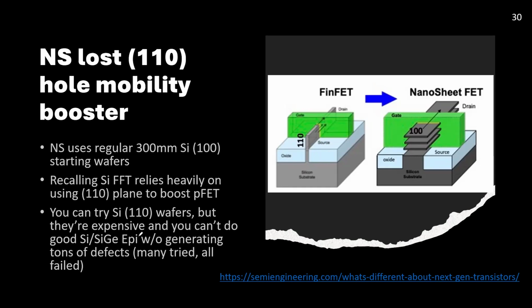You cannot just cut it. Say, I want to get 100 and cut it at like 45 degrees, whatever, and get 110. It won't work that way. You will not get a perfect 110. If you are a little bit off, you'll be in trouble. So that's not good. You need to have a pure 110 single crystal, and you have to grow from a silicon 110 seed. You plant the seed to grow your crystal, and that has to be 110.